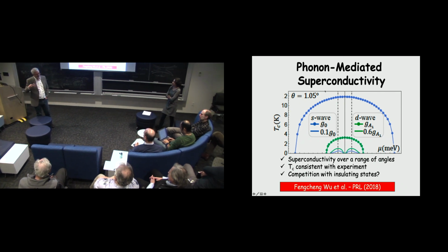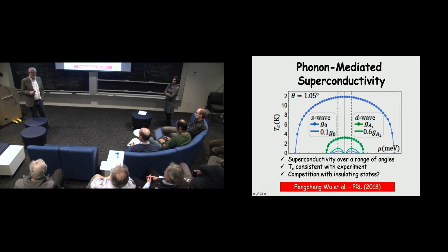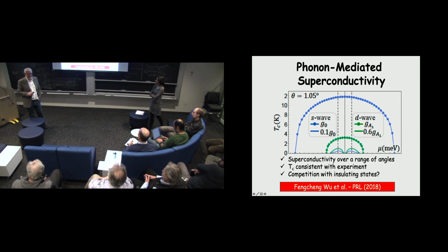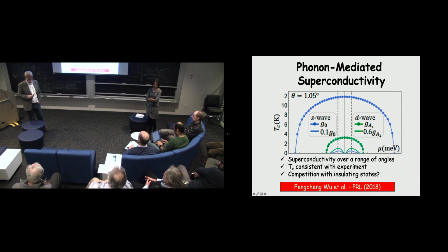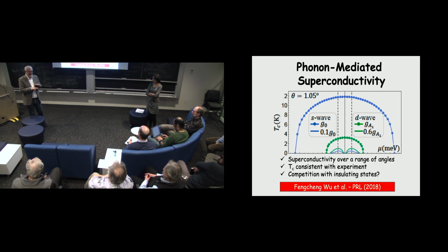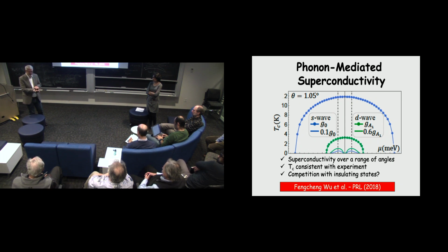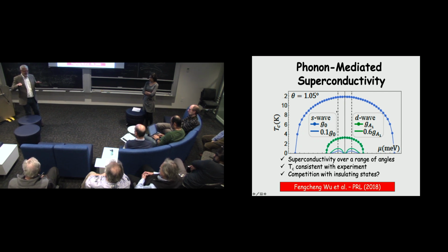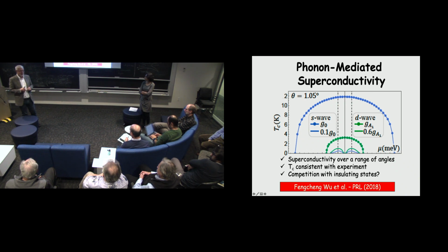The modulations end up also involving the reciprocal lattice vectors of the host 2D crystal. So I think there's no way you can avoid modulation in both directions in these, because the underlying lattice is triangular. If the underlying lattice was a square lattice and you just stretched it in one direction, then I think you would get a space dependence that depended only on one coordinate.